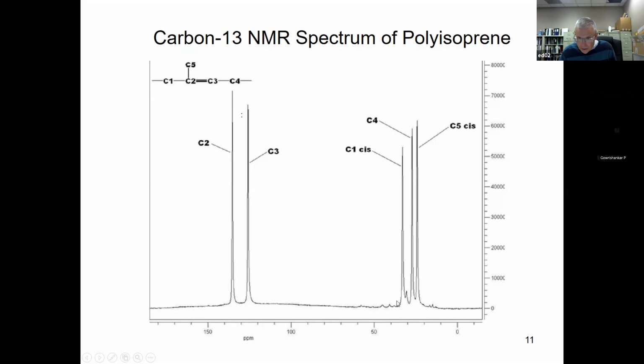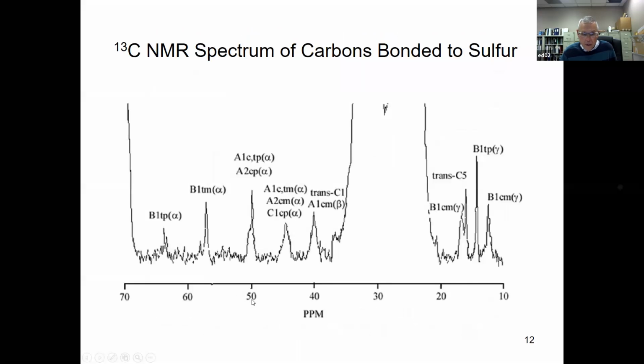Okay. Now, the whole point of showing you is if you look down in this area, there's a whole bunch of small peaks. And Professor Jack Koenig at Case Western University in Cleveland, Ohio, spent a major portion of his career analyzing these small peaks down here. And so here's an expanded view of that portion of the carbon-13 NMR spectrum. And he identified, these are all carbons that are bonded to a sulfur. And he identified all these peaks and the chemical structure associated with that carbon that's bonded to a sulfur. And, you know, is it a trans C5 and C1?